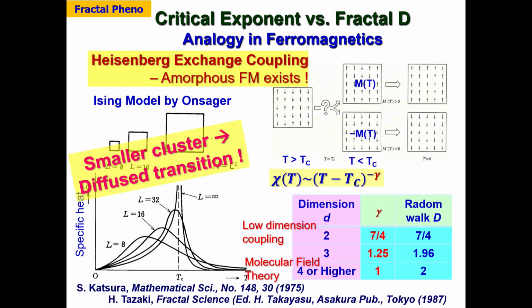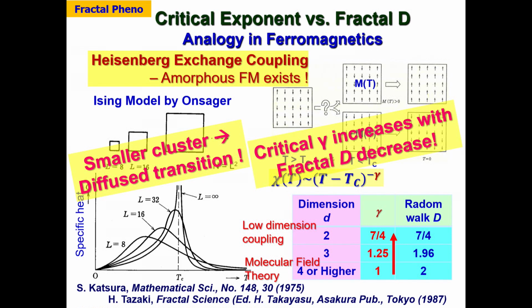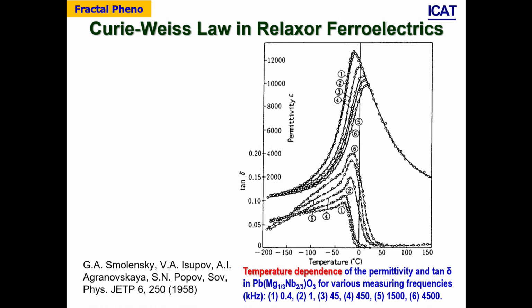However, for low dimension coupling, it approaches 1.75. This is a theoretical evaluation. And in parallel, the fractal dimension is decreasing. So the critical gamma increases as the fractal dimension decreases. This is the speculation from magnetic media.